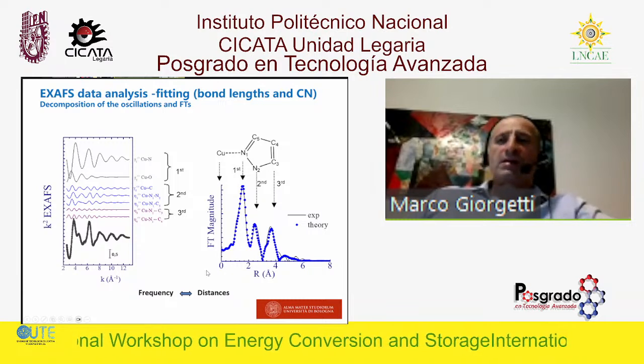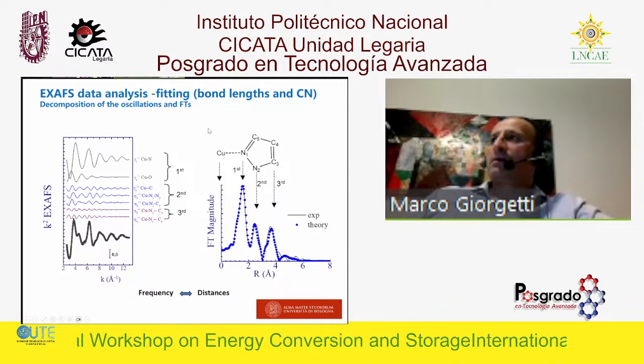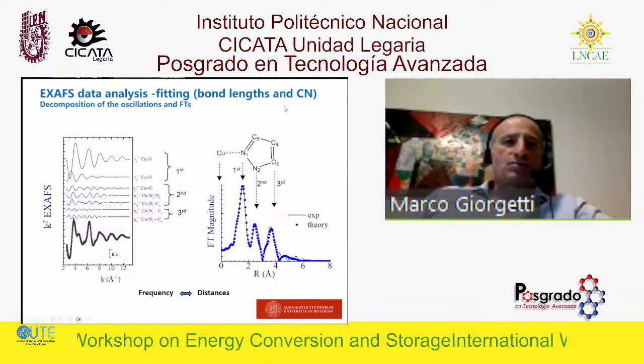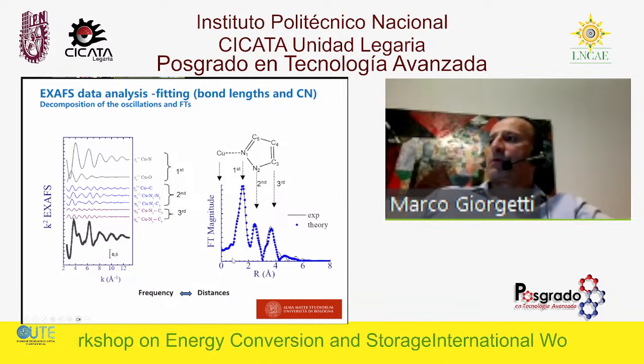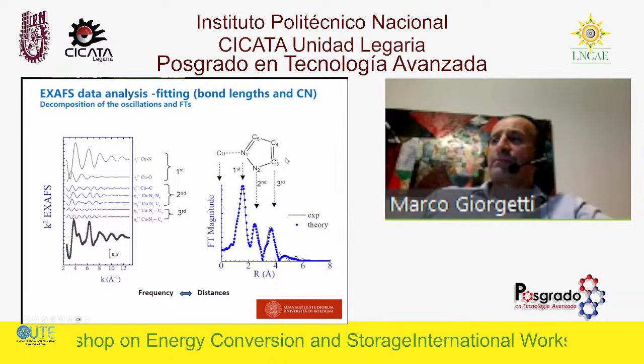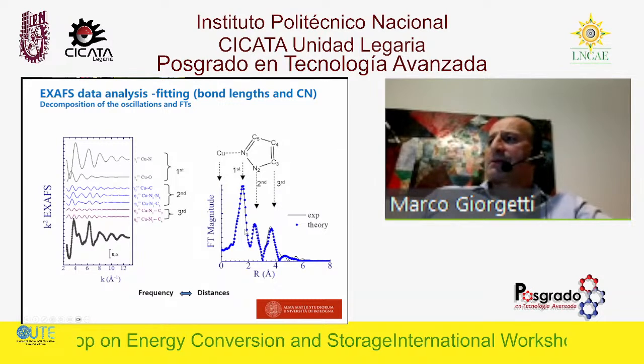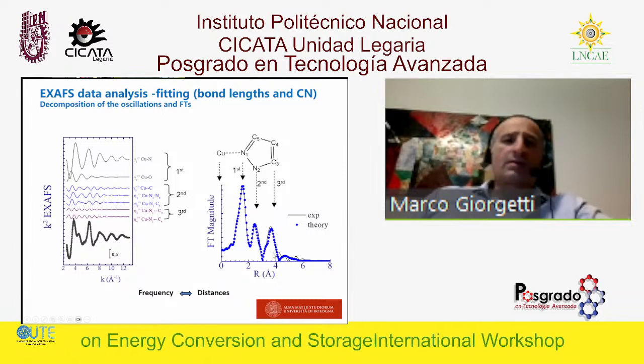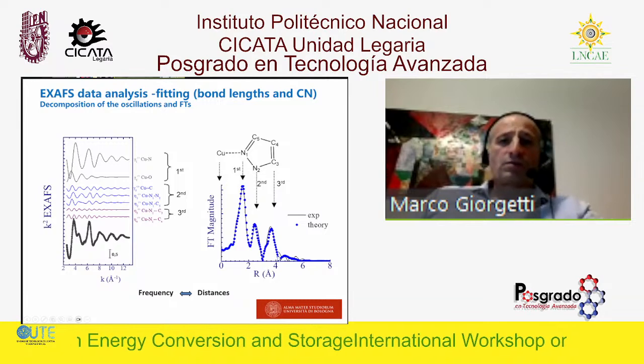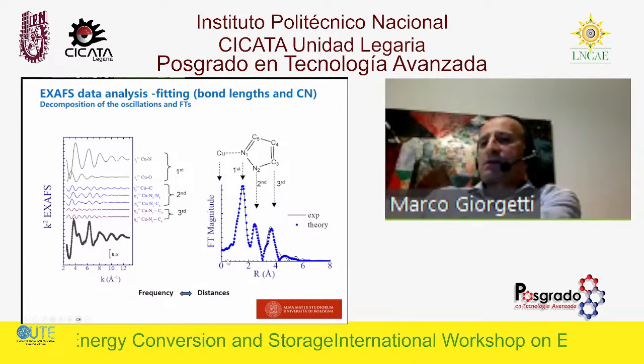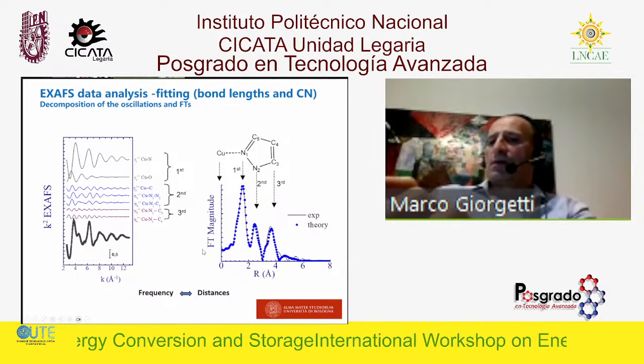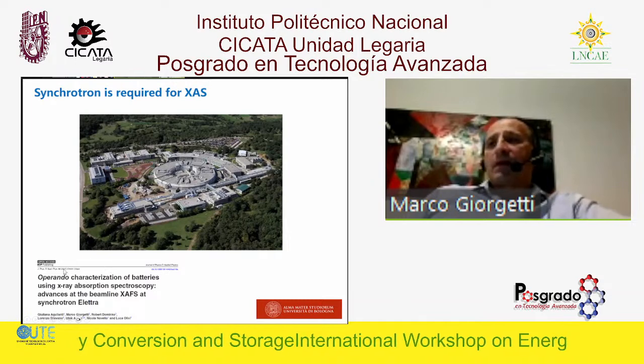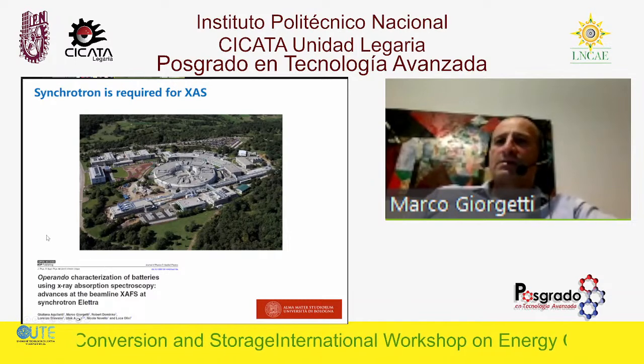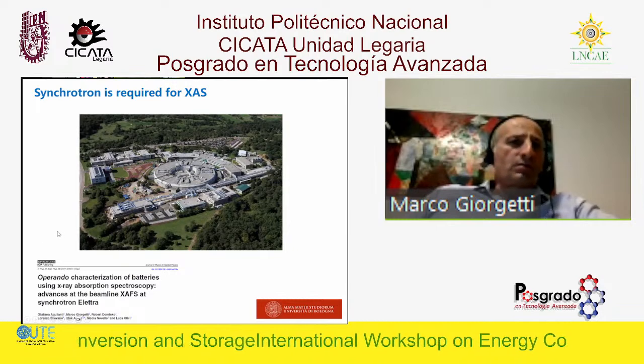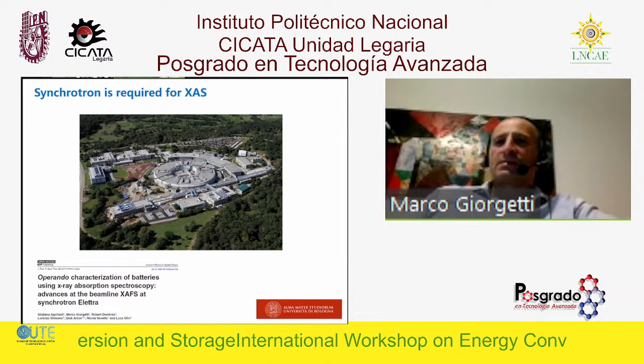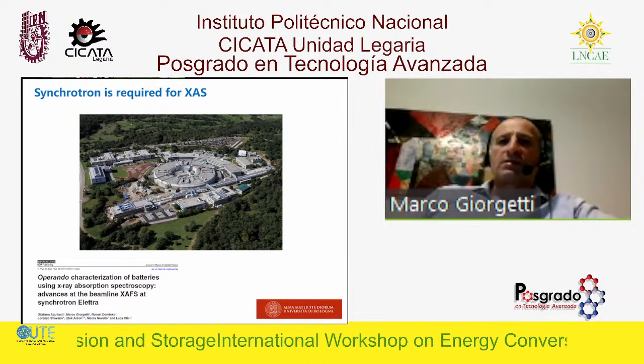Which kind of information can they release? They release structural information, I mean, bond lengths and the coordination numbers around the selected atom. You can see from here that even for this fragment, the information extends at maximum to about 4 angstrom or something like this. No more than that, because we have to keep in mind this is a technique that probes just the local coordination geometry. One of the issues or negative points is that in order to obtain a good signal-to-noise ratio in EXAFS experiments, the use of synchrotron radiation is required. And of course, the source is not widely available.